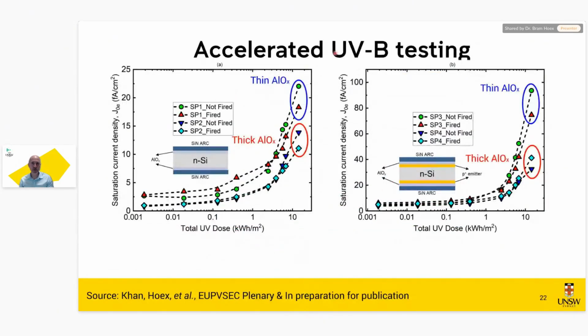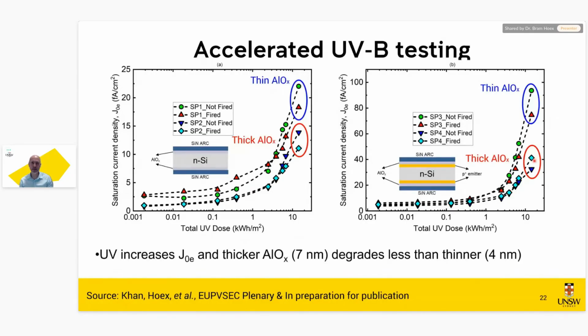So if we first look at the accelerated UVB testing, we see that both samples, the lifetime sample and the sample that is more representative of the front of the TOPCon solar cell, show an increase in recombination as a function of UV dose. But we see two separations. We see that fired samples do better than unfired samples. But more importantly, the thicker ALOX film, and this has been shown by other groups as well, shows significantly less UVID. So that's the first mitigation method that we have available to us. Go thicker with your ALOX film, and you will have less UVID. And we're quite confident that this is already used in the industry to produce more robust samples in terms of UV sensitivity.